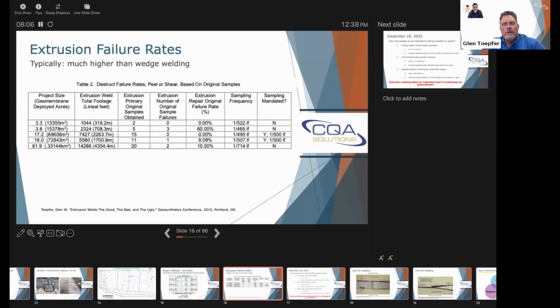Your wedge weld, people say you can be at 1%. I don't think that number is really realistic, at least from what we see. It's probably 2 to 3% as a target. 5% definitely can be met with a wedge weld, but with a good crew. But with your extrusion welds, if you're at 5%, that'd be phenomenal. You're probably going to be closer to 10% at a minimum. And if you have a bad crew, it could go south a lot quicker.